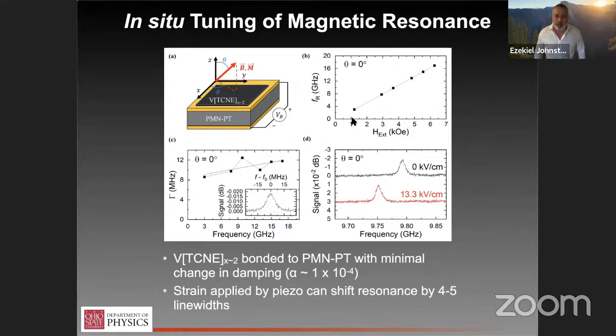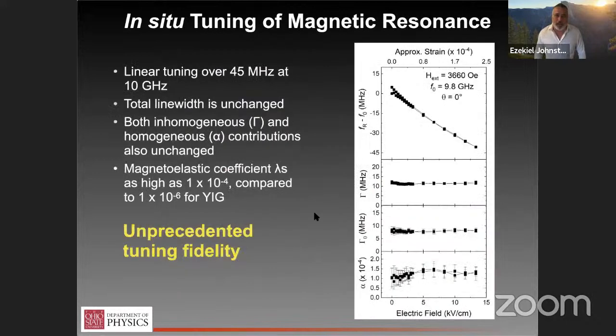So these initial panels are just characterizing that, yes, this is reasonably well-behaved V[TCNE]x-2. The line width is somewhat broader than the optimized films I showed a moment ago, just because of engineering them into this piezo geometry. But the important point is, as we apply bias to the piezo, you can see a significant shift in the ferromagnetic resonance frequency of the V[TCNE]x-2. And in fact, we can get a shift at maximum strain of 4 to 5 line widths. So to put that in context,